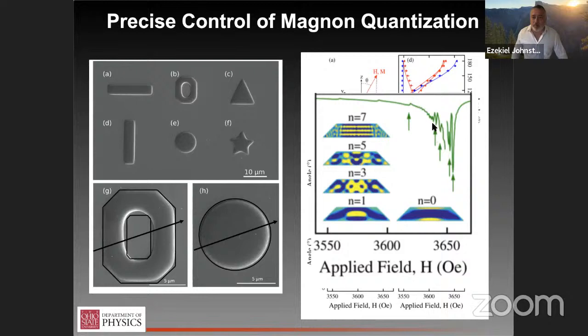You see a lot more peaks in the simulation because not all magnons have the appropriate symmetry to couple to the cavity that we're using to do the measurement. So that's not actually a failure of the theory, the fact that we see more peaks here. And importantly, this numerical modeling allows us to develop these spatial maps of the magnon mode in a cross section of one of these disks.